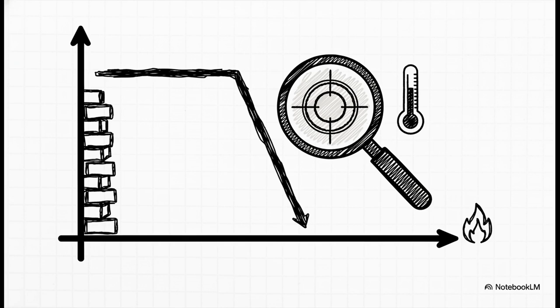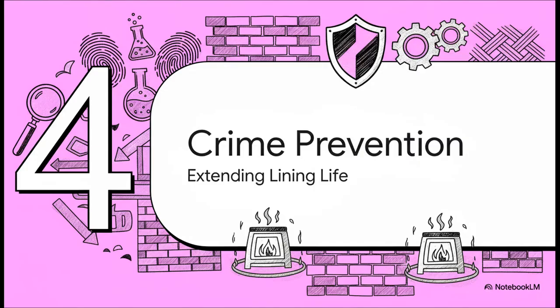The RUL results provide the smoking gun. It tells our detective the exact temperature at which that material starts to soften and give way under pressure. This is the proof. It tells you for sure whether the right material was chosen for the operating conditions in the first place. Okay, so we've identified our culprits, we've analyzed the evidence, and we've closed the case.